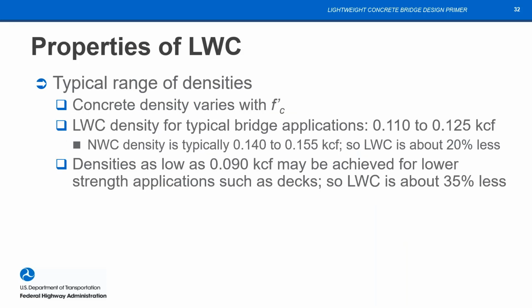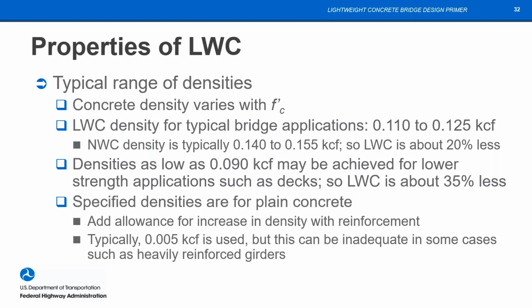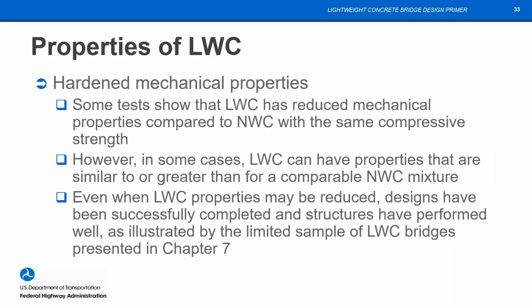Typical range of densities, it's given in the primer. For lightweight concrete, typically from 110 to 125. You can get lower. You can get all the way down to maybe 90 pounds a cubic foot, maybe 100 pounds per cubic foot. The specified densities are, as they are for normal weight, or for plain concrete, so you do have to add an allowance for reinforcement when you're computing dead loads.